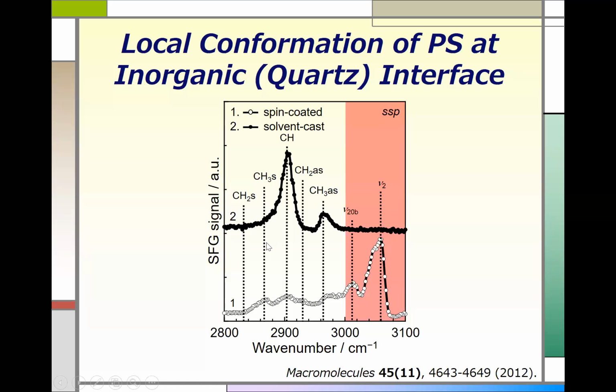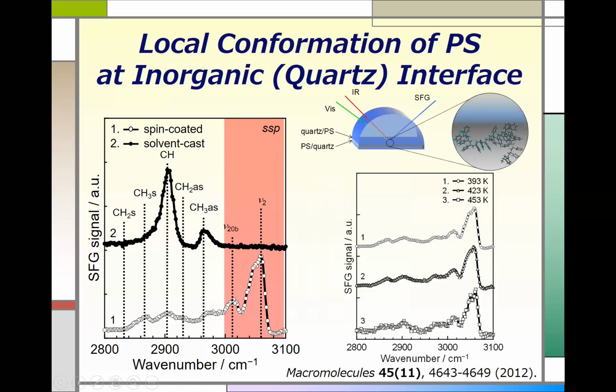So then, all right, that'd be fine. We have applied two different techniques to prepare polymer films on the substrate. So then the structure of polymer at the substrate is going to be changed. Okay, that makes sense. So then you may want to anneal those samples at a temperature higher than the bulk glass transition temperature. And as a sample, we have been using polystyrene with a bulk glass transition temperature of 100 degrees Celsius, I mean, 373 K. So then we anneal these samples at 120 degrees Celsius for 24 hours and 150 degrees Celsius for 3 hours and 180 degrees Celsius, which is higher than bulk Tg by 80 degrees Celsius, for 3 hours,